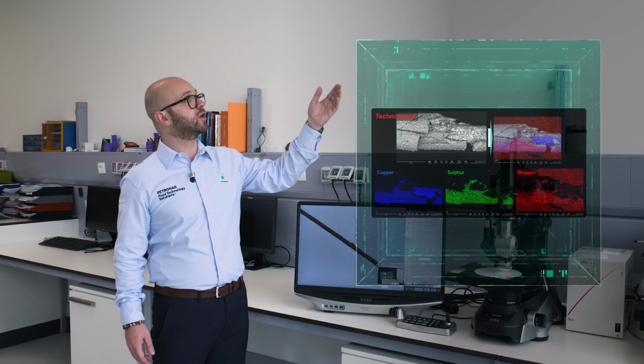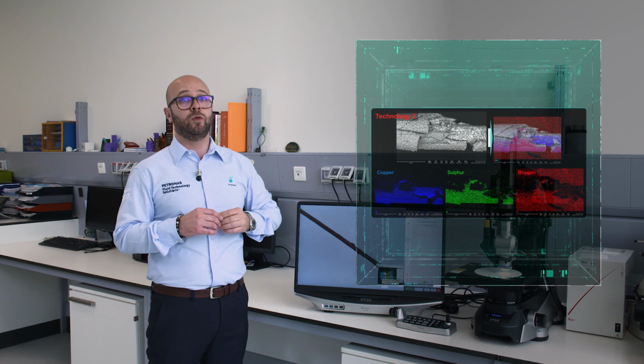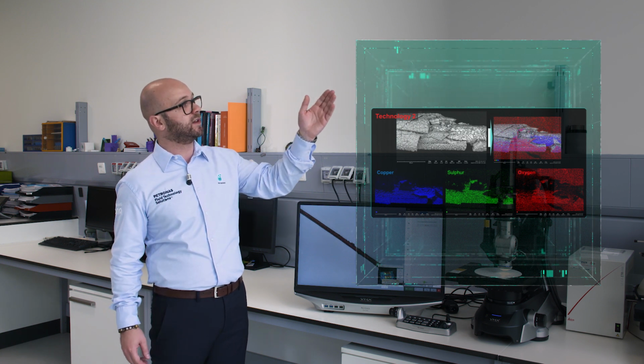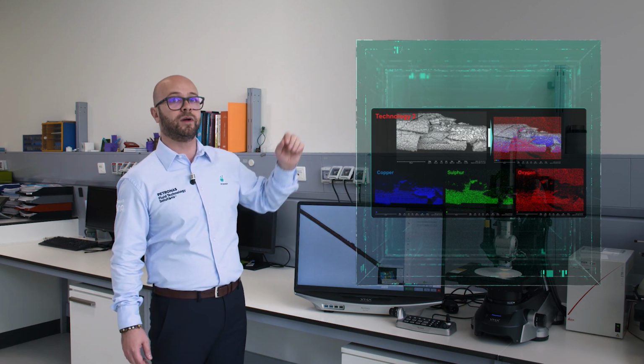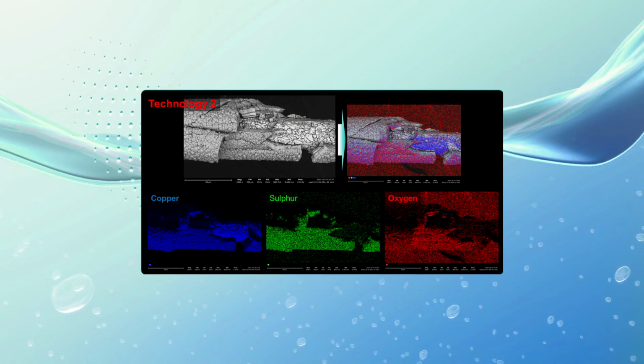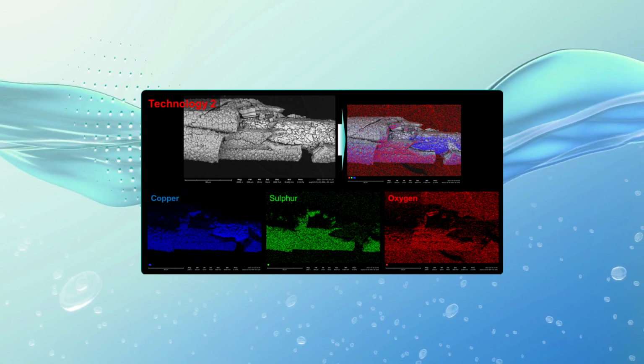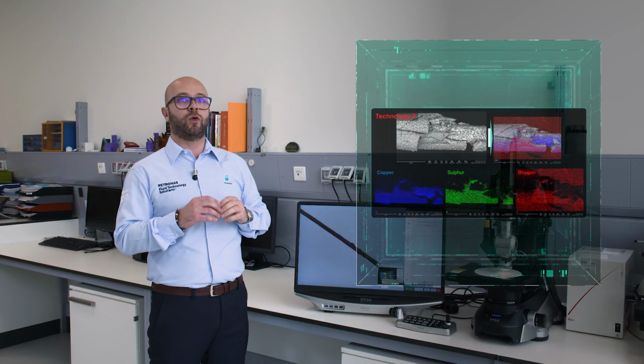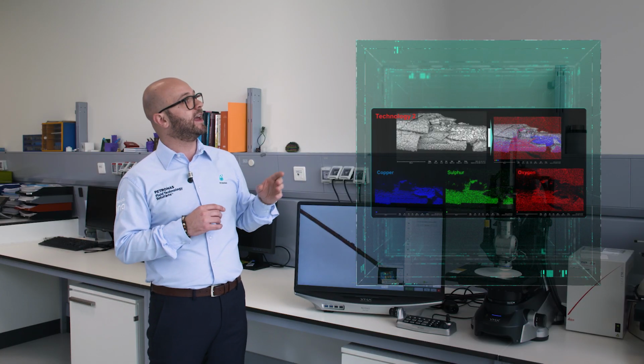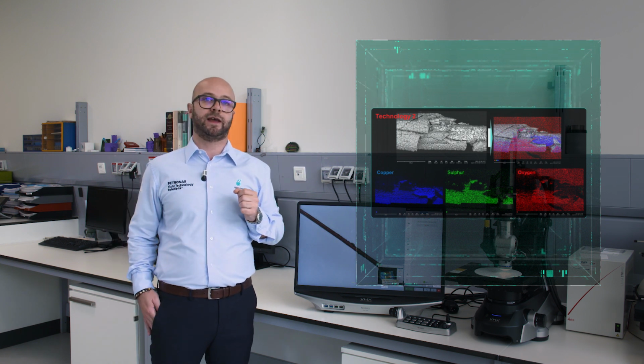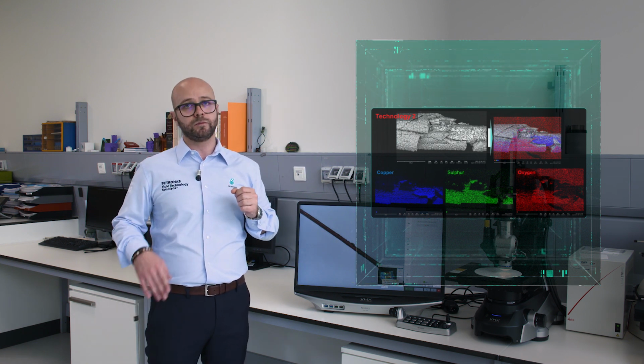Additional information was provided thanks to EDX analysis. The EDX analysis allows us to access the chemical composition of the surface of the wire. For technology 2, for example, we clearly see the presence of areas of sulfur and copper, which perfectly overlap on the corrosion product rich area, while in the area where the wire is exposed, we only have the signal of the copper.